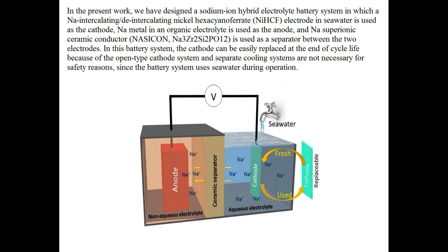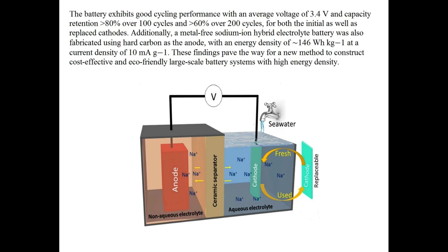In this battery system, the cathode can be easily replaced at the end of cycle life because of the open-type cathode system, and separate cooling systems are not necessary for safety reasons, since the battery system uses seawater during operation. The battery exhibits good cycling performance with an average voltage of 3.4 V and capacity retention of 80% over 100 cycles and 60% over 200 cycles, for both the initial as well as replaced cathodes.